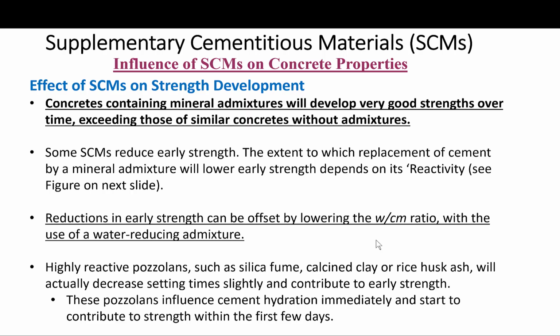At early ages, some mineral admixtures essentially behave as an inert addition, so the cement reacts with an effectively higher water-cement ratio at the beginning. However, highly reactive pozzolans such as silica fume, calcined clay, or rice husk ash will actually decrease setting time slightly and contribute to early strength.